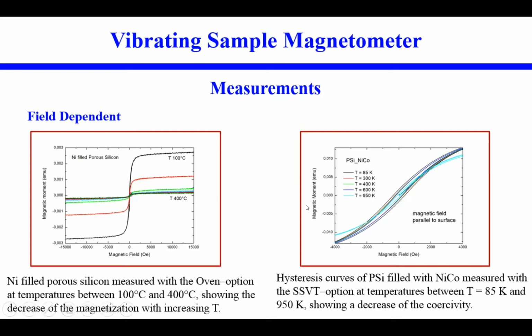And at the right side, you see hysteresis curves of porous silicon filled with nickel cobalt. It's performed with the SSVT option in a temperature range between 85 and 950 K. And you see the decrease of the coercivity with increasing temperature, but the Curie temperature is not reached, which indicates a very high cobalt content.